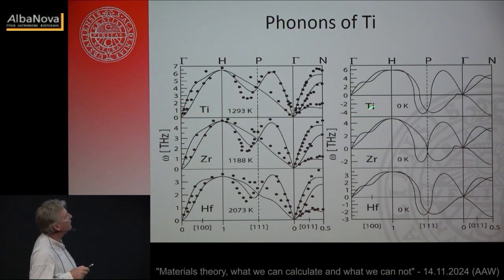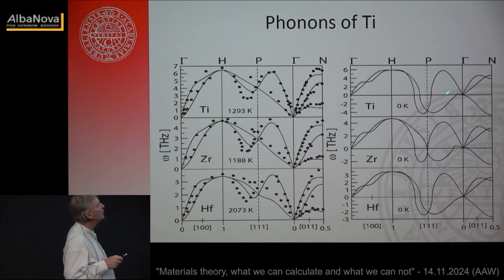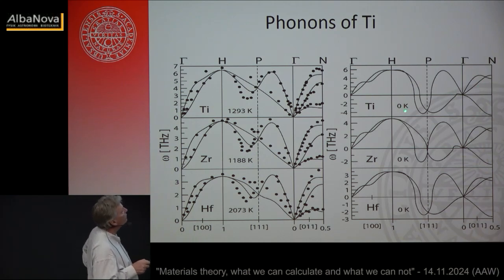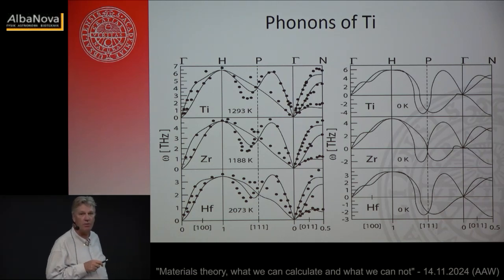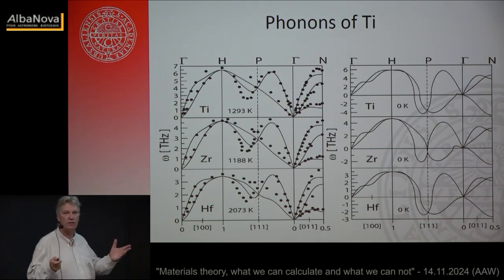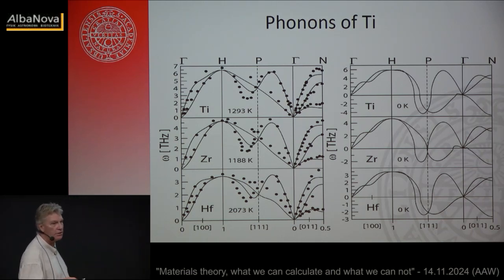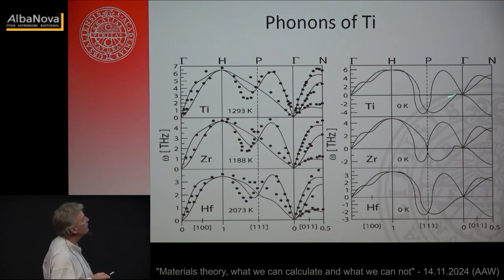And what you see is that for titanium and also for the isoelectronic elements, zirconium and hafnium, some of these modes are plotted to be negative. They're actually not negative, they're imaginary. And that means that the crystal is not even dynamically stable. It's not supposed to exist, it just falls apart. So something really came out wrong in this calculation, and it was not numerical or so, it was something fundamental.